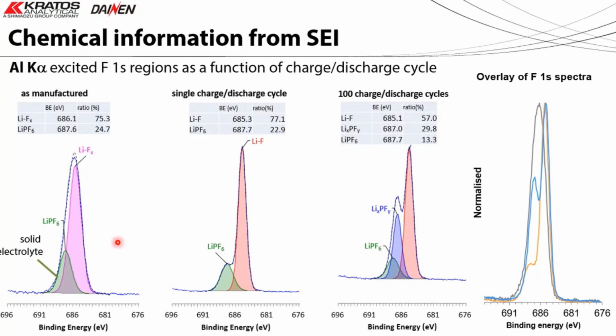So what's happening is that, from curve fitting our fluorine region, it's noted that the as manufactured sample here is already showing some degradation of the lithium hexafluorophosphate component into this lithium with fluorine bonded. So we've already, just by manufacturing, got some degradation, and that SEI layer is beginning to form.